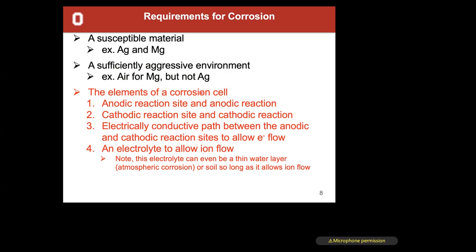You also need to have the elements of a corrosion cell. I tell you this because it is utilized all of the time in corrosion protection. So you need an anodic reaction site and an anodic reaction, a place for that metal ion to come from. And you need a cathodic reaction site and a cathodic reaction. And they don't happen at the same atomic site. You need an electrically conductive pathway, right? We need these electrons to flow, which is why electrochemical reactions are important here. Then you also need an electrolyte present for the ions to flow away from your surface. If they can't flow away from the surface, you can actually inhibit corrosion.